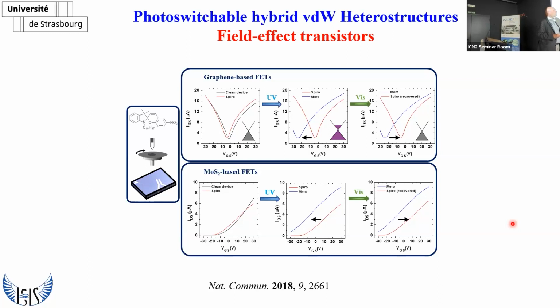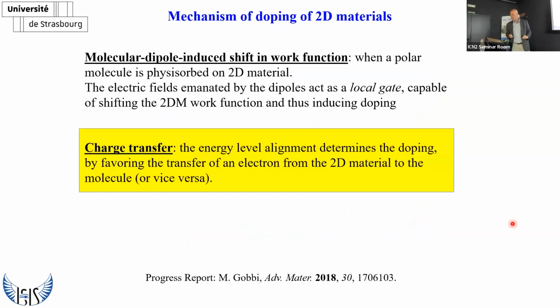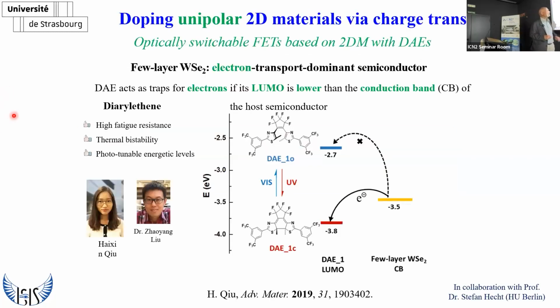And with a big, strong n-doping effect, the carrier concentration change is pretty high. You can do the same also with MoS2 devices. The same story, no need to go into the details. But let's focus on the charge transfer approach that is based on the energy level alignment, which determines the doping by favoring the transfer of electrons either from the material to the molecule or vice versa. And of course, we make use of the diarylethenes, which in the 2 states have